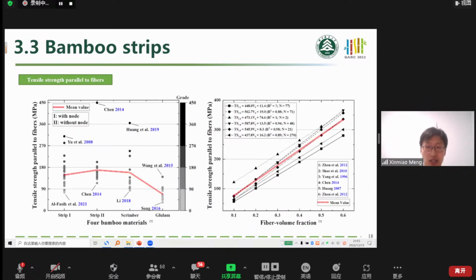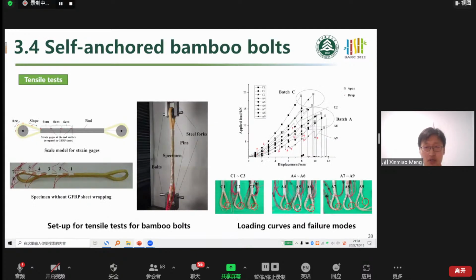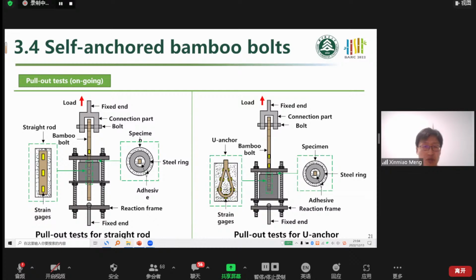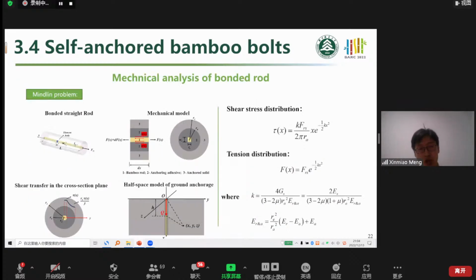And here's the relationship between the fiber volume fraction and the tensile strength parallel to grain. And then we conducted the tensile test for the bamboo bolts. In this bolt, the GFRP was just used as the coating. And we found that most of the specimens failed with a fiber rupture at the U-shaped end. And another one is that we also designed a pull-out test. It was still under test due to COVID-19, but the theoretical analysis has been done.